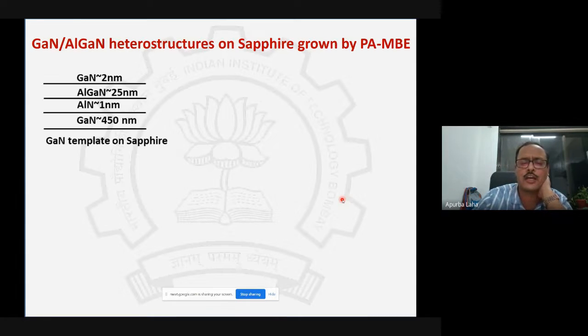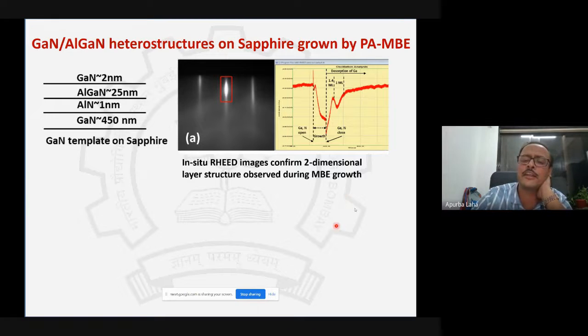Okay, so now how do we grow it? Let me give you a brief description of the process. As I said, this is the RHEED image that you get during this molecular beam epitaxy growth. As there is no substrate available, no single crystal gallium nitride available, we always have to look at the process window that eventually helps us grow a two-dimensional layer. Large lattice mismatch is always very challenging.